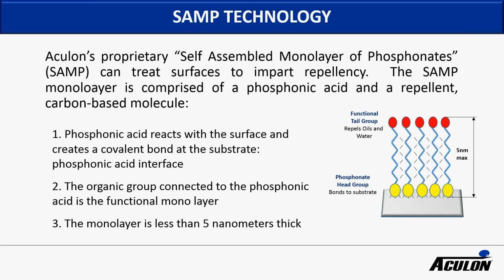Just to dig a little deeper into the SAMP technology, this illustrates the approach that we've taken here. Here we're reacting a phosphonate head group to a surface. We're forming covalent bonds that are very chemically strong and resistant to attack. The organic group that sticks out, for the case of repellency, we can make this either perfluorinated or choose a material that's repellent. These are very thin layers. We're dealing with a monolayer, so the thickness is typically between 2 and 4 nanometers thick.